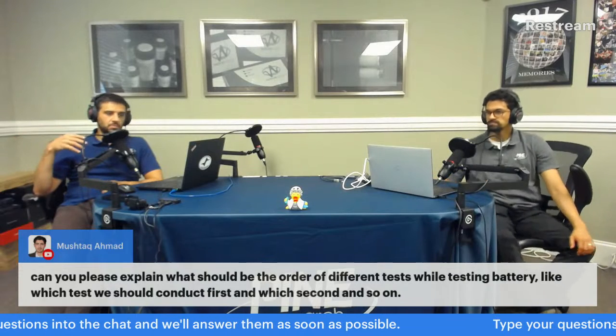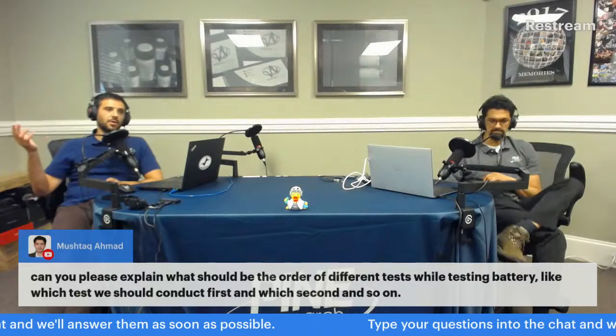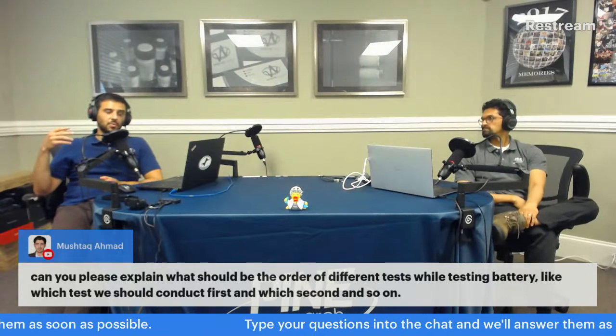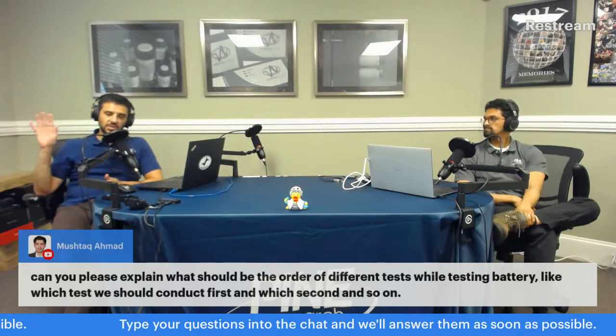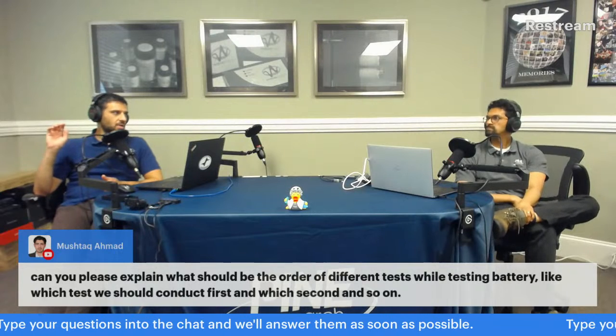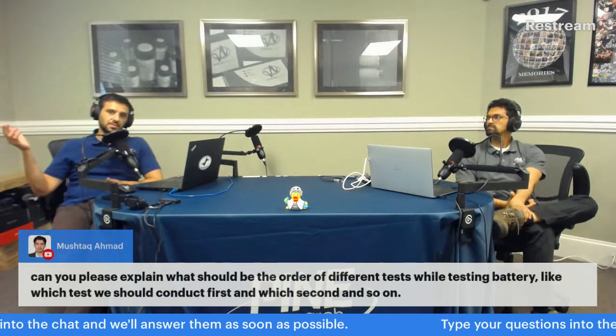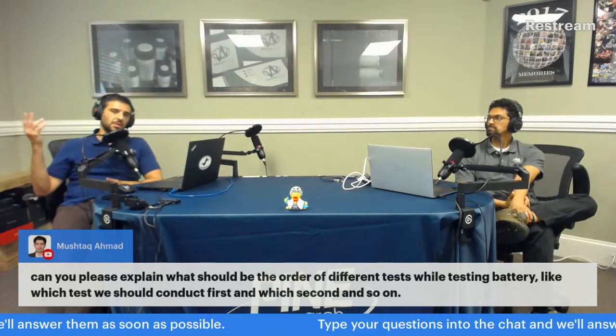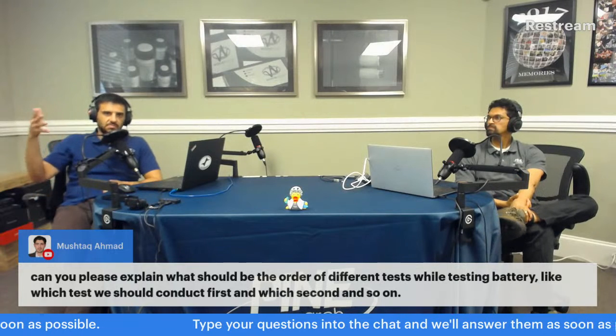You put a milliamp into it, it should take an hour. So it's a 1 milliamp hour battery. Well, if it takes an hour the first time up and down, that's great. And then after 100 cycles, it only takes 50 minutes. Well, it's lost about 16% of its capacity, right? So that's what people are doing.